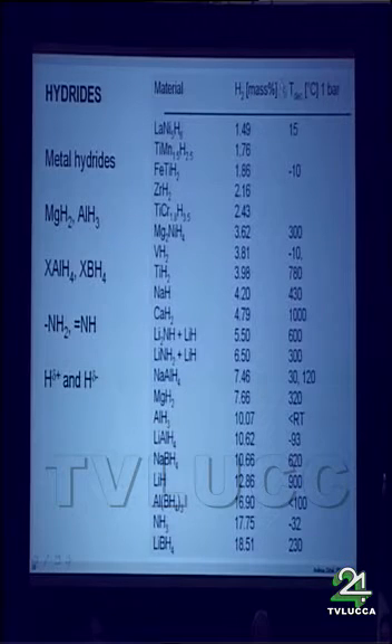Now, the last column here shows you the decomposition temperature. And it's very interesting to notice that the decomposition temperature is in no relation to the mass percentage of hydrogen. There are very, very unstable hydrides, like, for example, lithium aluminum hydride, or even ammonia, which is very unstable in equilibrium, with a very high mass percentage. And it is just a rumor that complex hydrides or hydrides with a high hydrogen storage capacity are necessarily stable. It is just because until now the chemists have mainly investigated stable compounds, because they were interested in stable materials in the lab. But there are plenty of hydrides around which show a very high mass percentage but aren't stable at all.